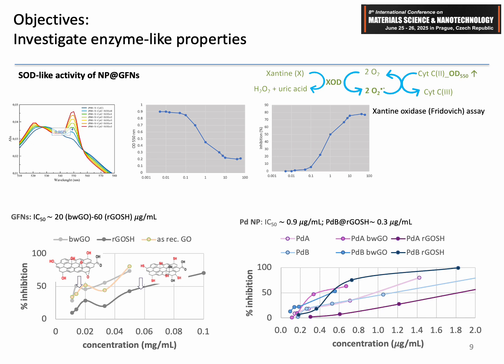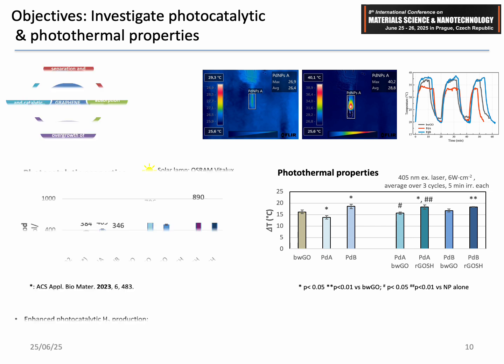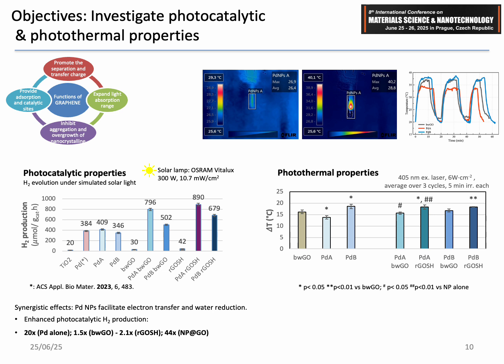Our hypothesis here is that the nanozyme mainly acts through adsorption, activation and electron transfer driven by the unpaired electrons and the multivalent surface ions, and the exact mechanism, which can be further investigated, depends on factors like the pH, the structure, the surface chemistry, which opens up plenty of possibilities. Also, thanks to the plasmonic tuning, the thermographic analysis confirms a significant temperature rise in the palladium GO hybrids under laser irradiation, demonstrating a synergistic effect beyond the sum of the single components. Heat generation was significantly higher than for either palladium or the GO alone.